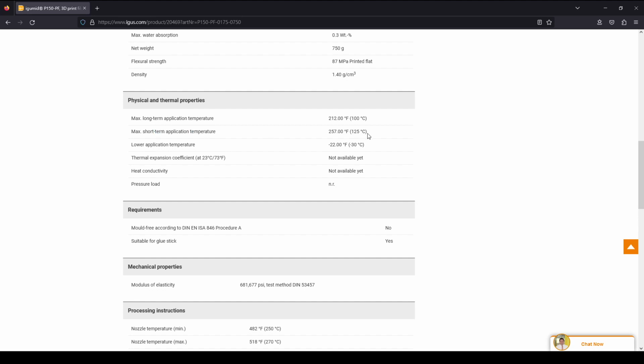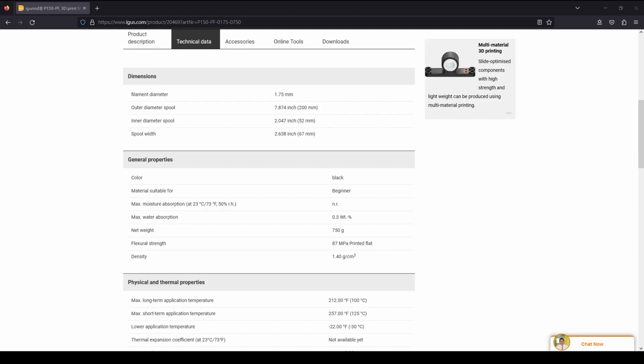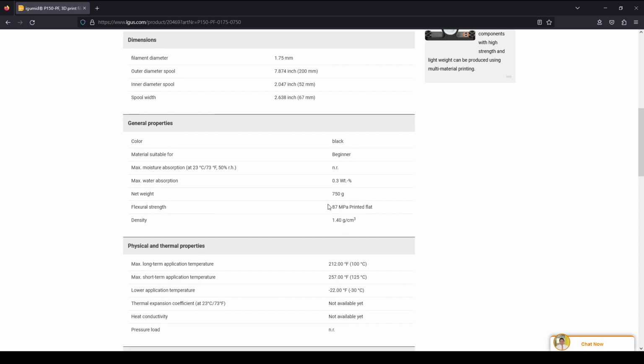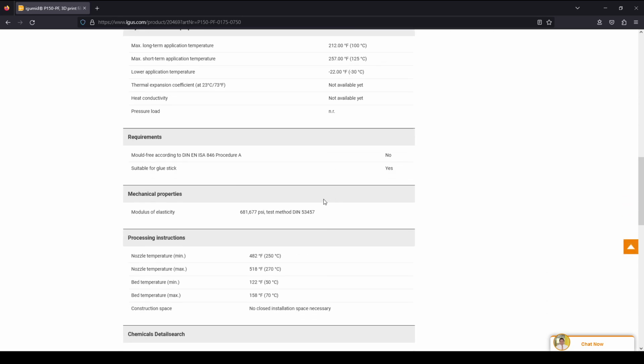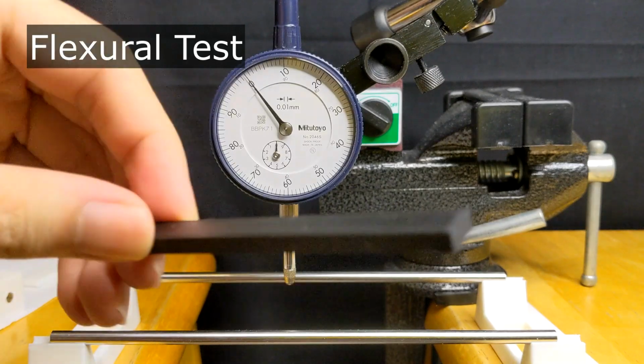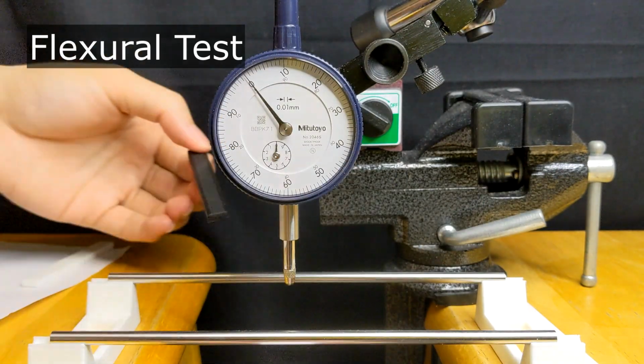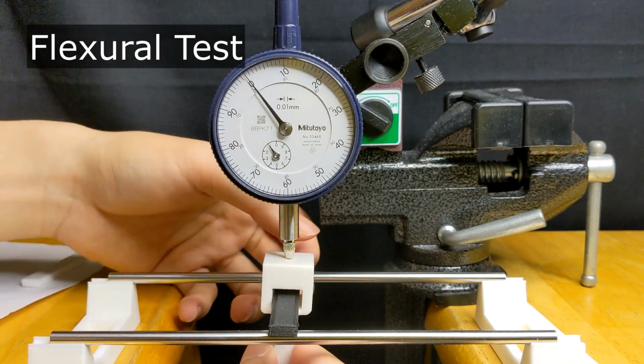This material might be similar to the PA12CF I introduced previously, having almost the same printing temperature range and thermal resistance. P150 material emphasizes its flexural strength, which can reach 87 MPa along the printing surface orientation. As an anisotropic material, the elastic modulus is 4700 MPa. These types of fibered materials are typical for structural parts. So what about the P150's performance in flexural tests and creep tests in anisotropic 3D printed parts?